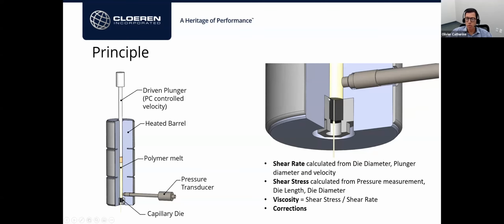This is a little too small, so on the right side here you have a blown up version of this picture. The capillary die is a very precise channel of known dimensions, namely the length and the capillary diameter. From these features, we can calculate shear rate. As we push the material at a controlled speed, we measure the pressure resulting from this flow. The pressure is measured through a membrane type pressure sensor, and from the pressure, we are able to calculate the shear stress. The viscosity is basically shear stress divided by the shear rate. So this is fairly simple in theory.